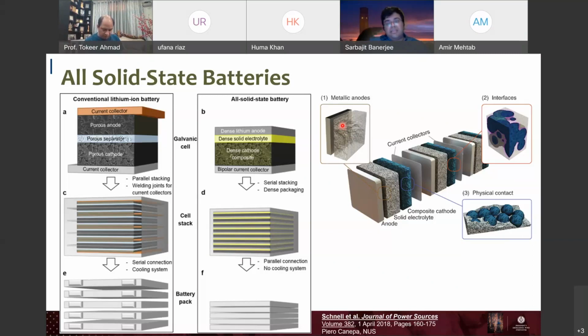The challenge with this is that, as I'll describe in the next few slides, lithium metal can be very difficult to plate reversibly. Plate and strip over hundreds of cycles. A second challenge here has to do with the reactivity of interfaces. Lithium is an incredibly reactive metal, and when you put it together with cathodes with a solid electrolyte, there are inevitably going to be a bunch of reactions, and some sort of passivating film will form. What is the nature of the film? Is it permeable to lithium? What is the resistance that gets built up at that interface?